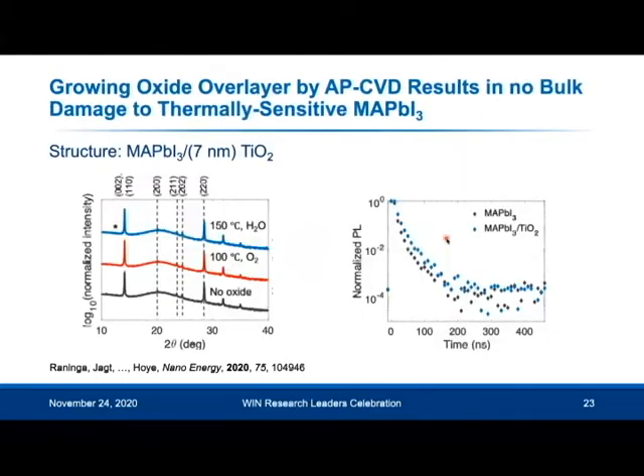And here you can see the bulk properties of the perovskite stack. So this shows you the diffraction pattern for this bilayer of methylammonium lead iodide with TiO2 grown on top under strong conditions. And if there were any lead iodide degradation product, it would appear here. And I emphasize this is on a logarithmic scale, which would accentuate any low intensity diffraction peaks. But you can see there's no peak that appeared. So we avoid any bulk degradation to the perovskite.